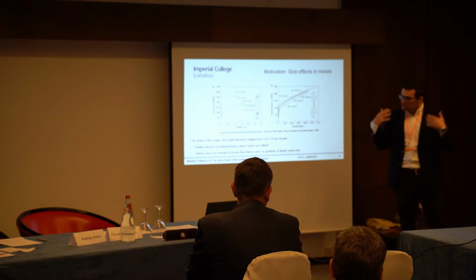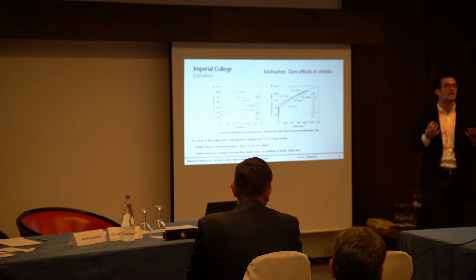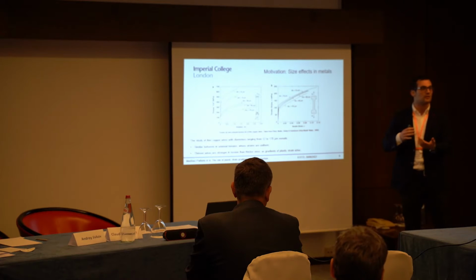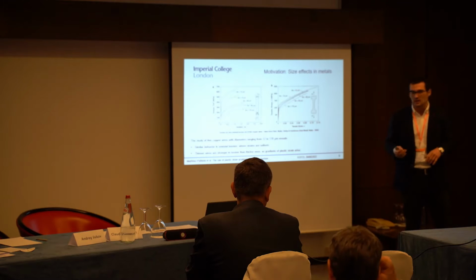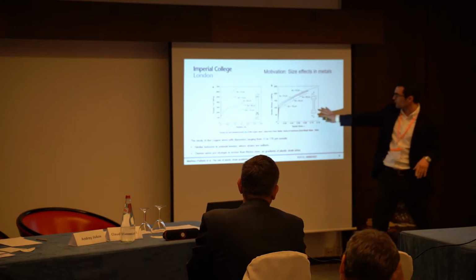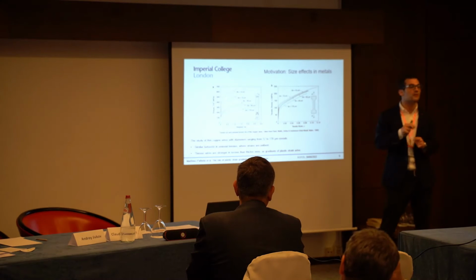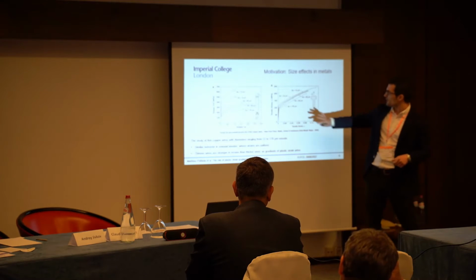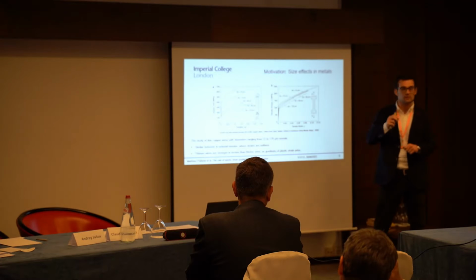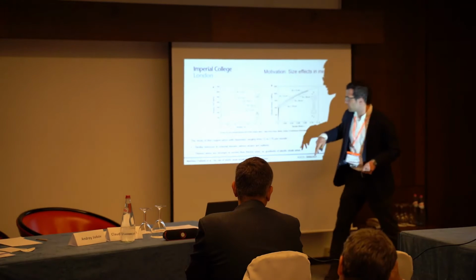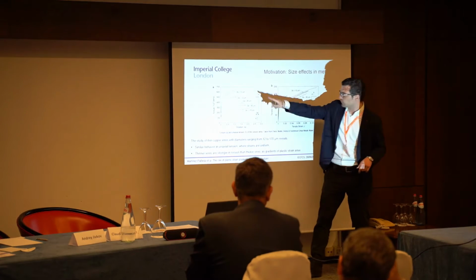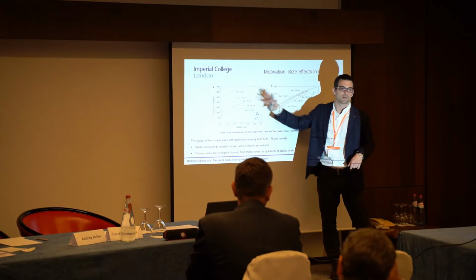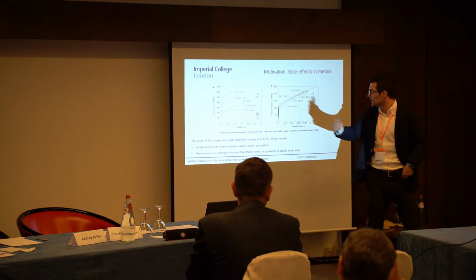The main motivation for this hypothesis comes from the strong size effect that you see in metals. Whenever you test metals at the micro scale, you see a smaller is stronger effect. You can see this consistently when you do indentation, microbending, microtorsion. I'm going to show this classic example that I like very much. These are experiments on thin copper wires. As you can see, they tested them both under uniaxial tension and in torsion. In the torsion case the torque has been normalized, so these are both kind of stress-strain curves.